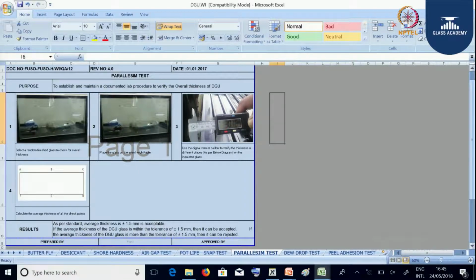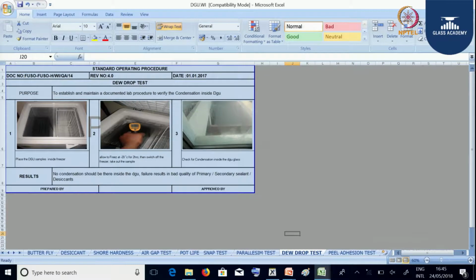Next test for DGU is the dewdrop test. The procedure is: we take a DGU glass, a final DGU product, and place it inside the freezer. We freeze the glass at minus 20 degrees centigrade for 2 hours.